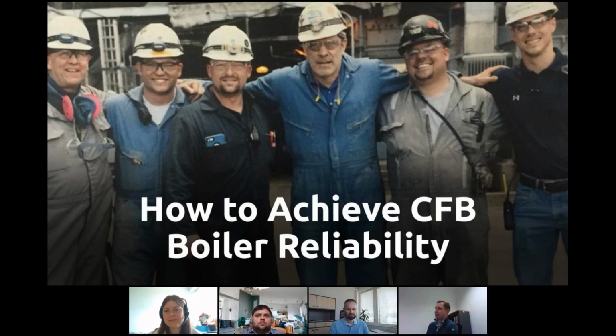Maybe you cannot even notice that it's a corrosion phenomenon because the erosion is eating the corrosion products away from the tube. But then you will certainly find excessive rates of tube wastage. So I would say that from the back pass measurements, flue gas oxygen measurements, you cannot tell the whole truth of what's happening in the combustor.